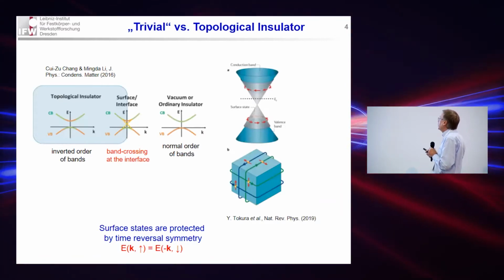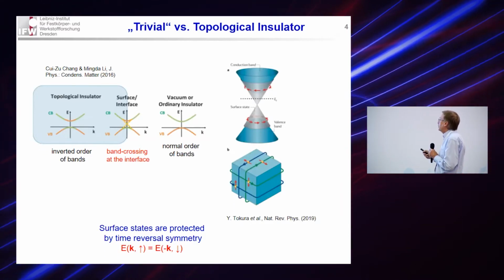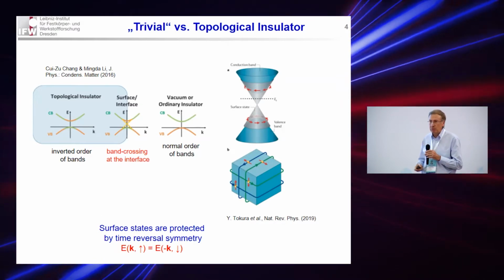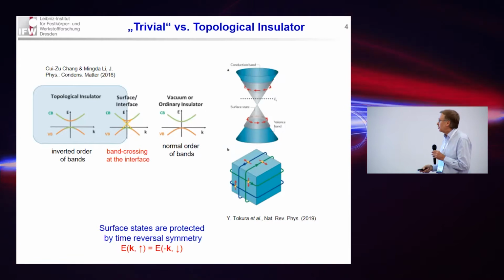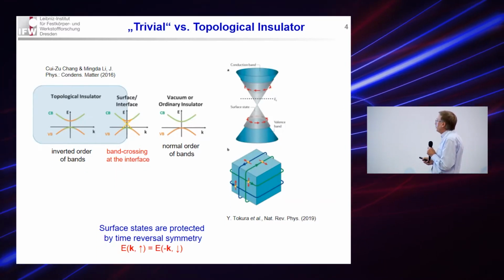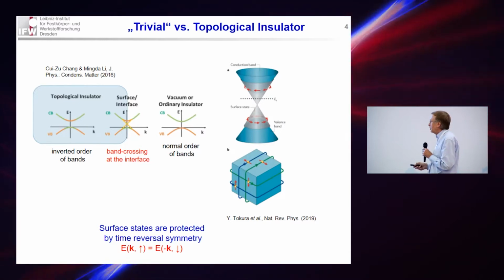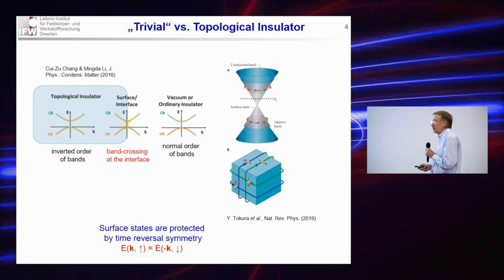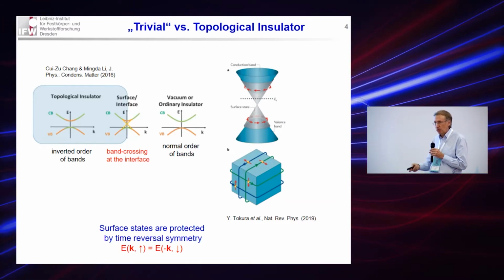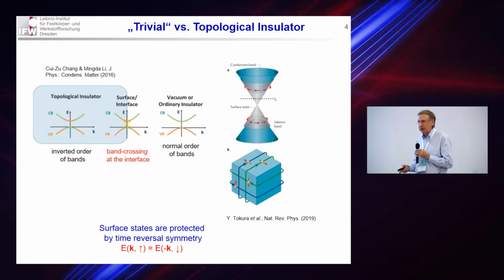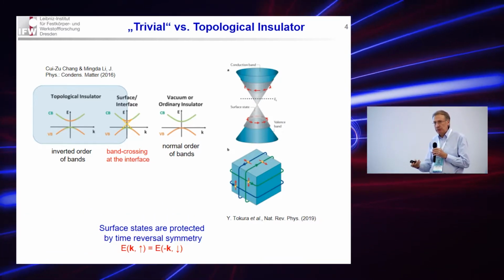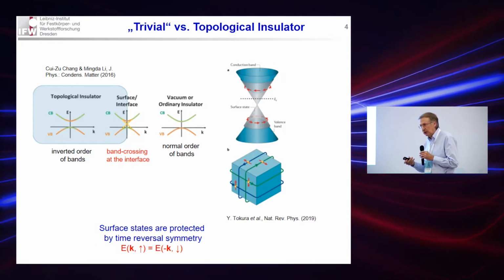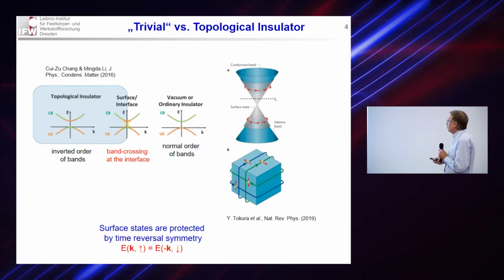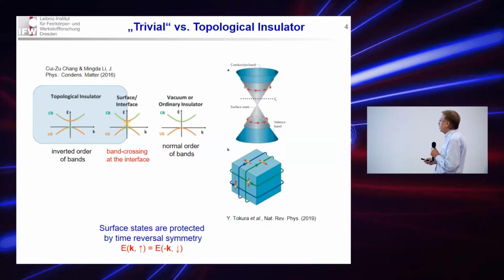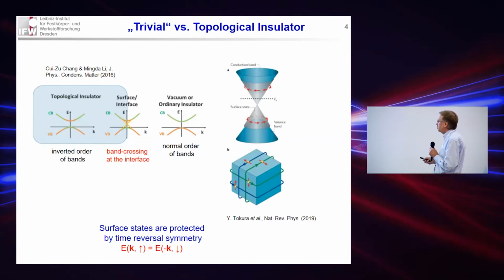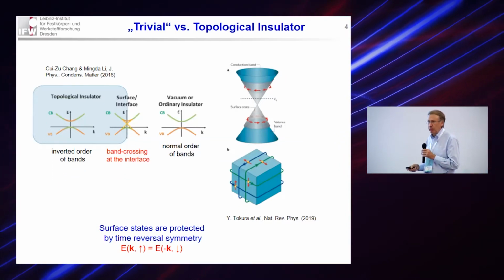So now, what is a topological insulator? What is distinct from, say, a conventional band insulator, which is known very well in semiconductor physics? The ordinary insulator has a valence band and a conduction band, as usual. Normally, the valence band has p character, so it has an orbital momentum, and the conduction band has s character. However, if one switches on strong spin-orbit coupling, which typically is the case in heavy elements, then the order of these bands could change, meaning that now the valence band has preferably s character and the conduction band preferably p character.